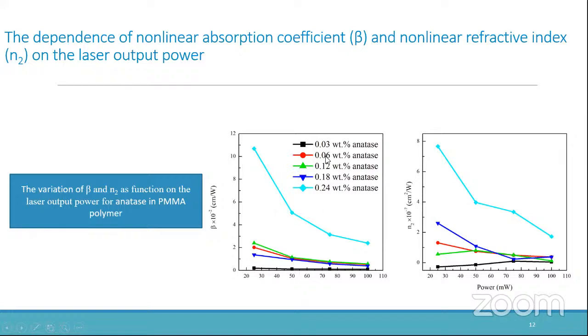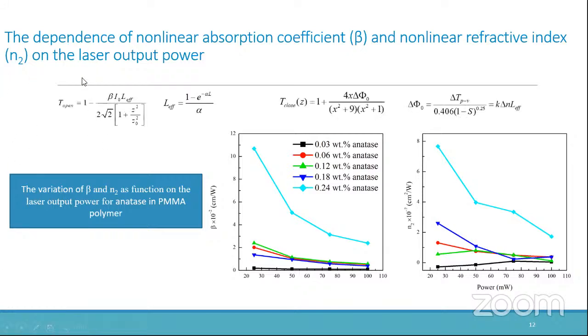We can see here the variation of absorption coefficient for different concentrations of nanoparticle in the sample at different power outputs of the laser, which varies from 20 to 100. So we can see here the most nonlinear effect is observed in the concentration of 0.24 weight percentage anatase nanoparticles, and these are the results of the nonlinear refractive indices of the same samples of different concentration at different laser output powers. So these are the formulas which we have used to calculate these points in the graphs.